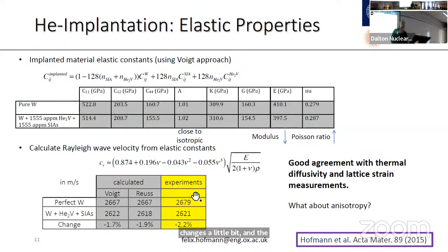And fortunately, in the lab, we have a way of actually measuring very accurately what the elastic constants of the material are. And Abdallah will talk about this, hopefully, maybe a little bit. But anyway, we can generate surface acoustic waves of micron wavelength, and those allow us to interrogate what the surface acoustic wave velocity is, and we can forward predict what the surface elastic wave velocity change we would expect is if we go from pure tungsten to this damaged tungsten, and we predict a reduction of about 2%, and that's also what we see in experiments.